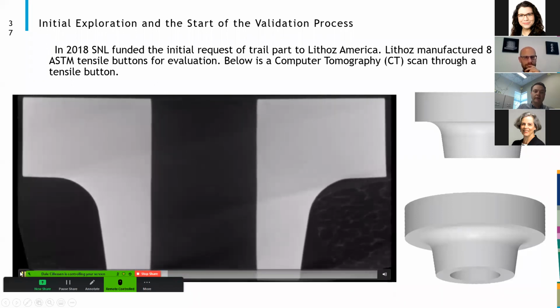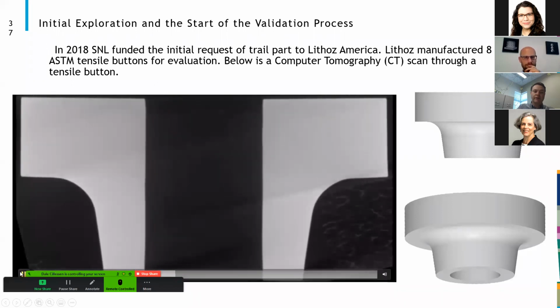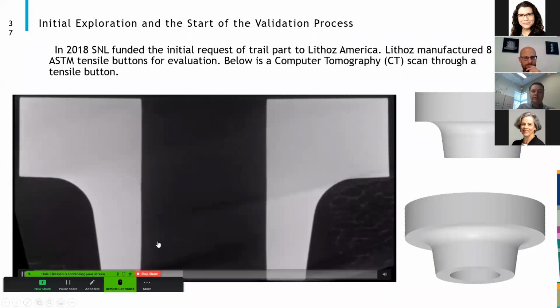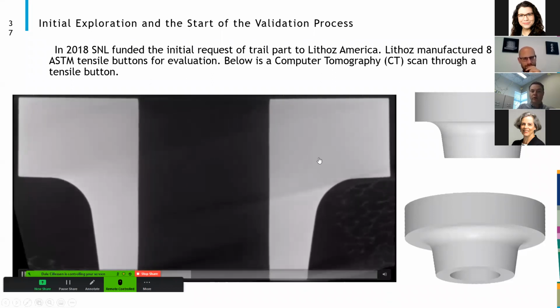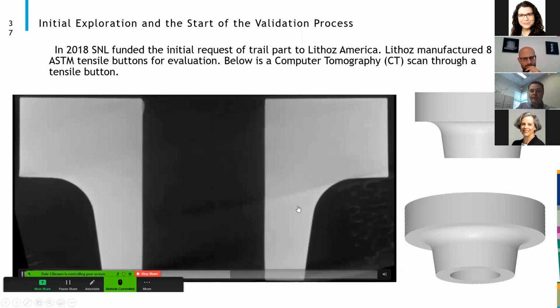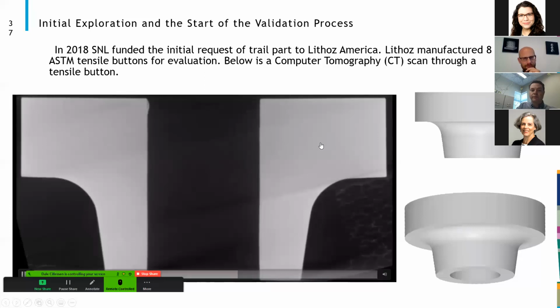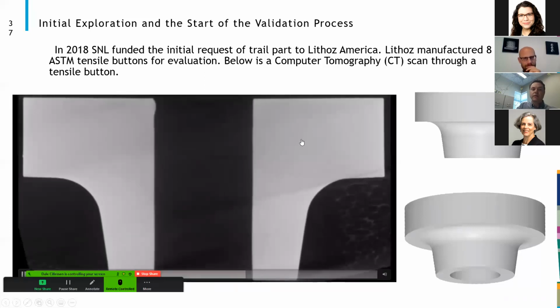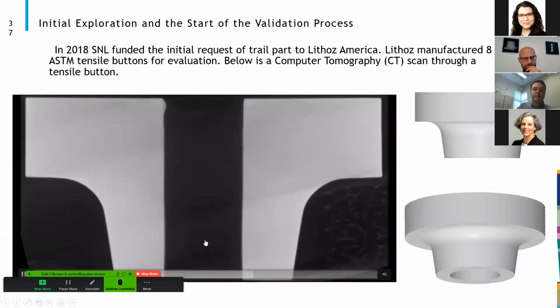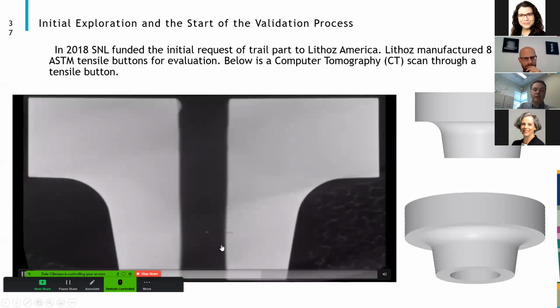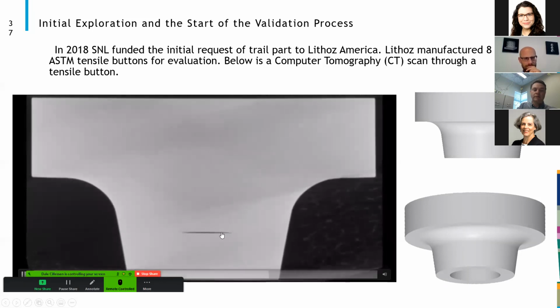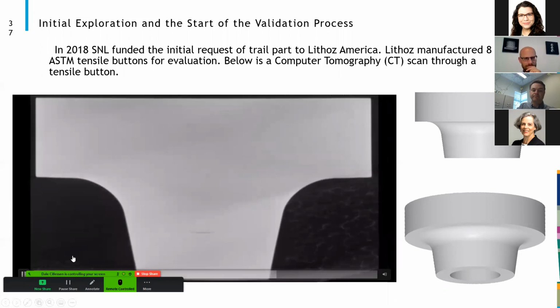Noted in the video, I chose this specific video as it does show that everything is not perfect. Although we do see fully dense components, with very nice clean sharp edges along the outside of this component, we did observe one small crack. However, we knew that this was something that could be overcome. As it approaches the back wall of this hole, you will notice a crack that appears 1/4 of the way up into the video.